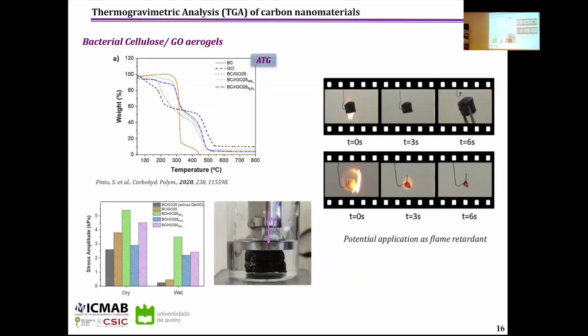So then, after a careful characterization of these materials, we also applied the properties we had in the building of new three-dimensional systems. In collaboration with Professor Concepcion Domingo, we prepared aerogels, graphene oxide aerogels, and we also doped them using hydrazine and also ammonolysis. And in this case, we obtained systems which were very, very stable in the presence of flame. So this is an approach in case we can scale the material we are working on and prepare three-dimensional systems based on layered materials. These materials also presented very high mechanical properties. They are very stable and have different behavior when they are dry or in the presence of some solvents.